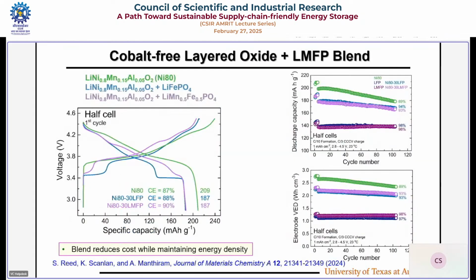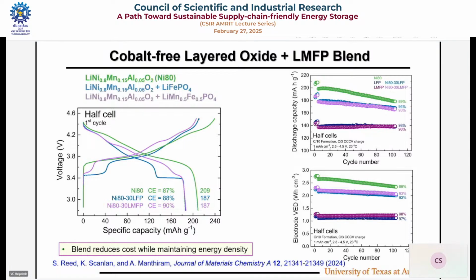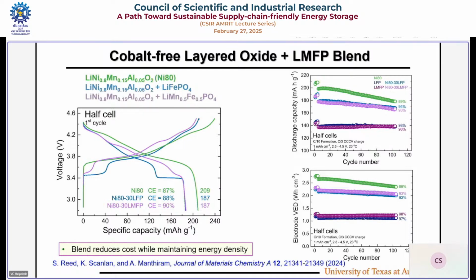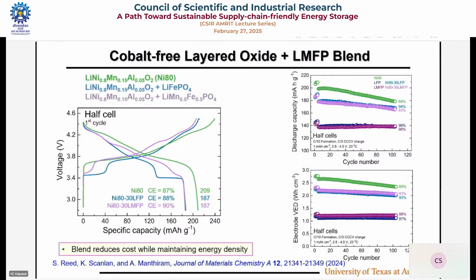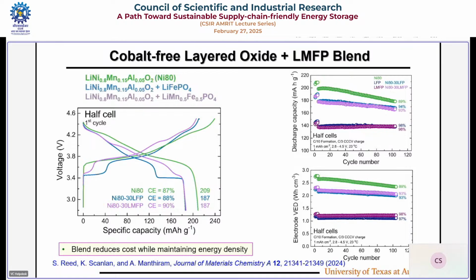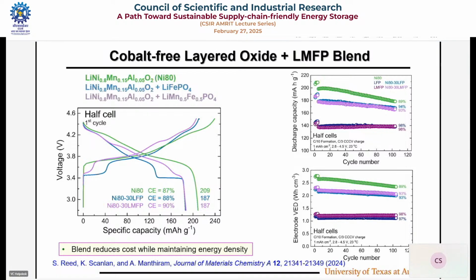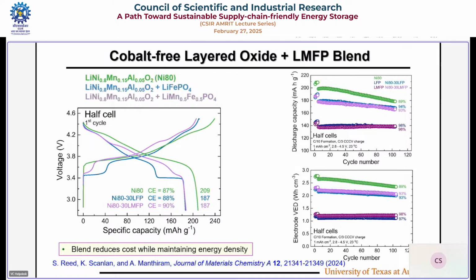Okay, there is another one to reduce the cost further. You can take a cobalt-free layered oxide like I talked about, like this. Then you blend that with this. One beautiful thing I like is this voltage profile. This is layered oxide LMFP blend 70-30. The voltage profile looks more or less similar to the layered oxide. Not exactly, but a very nice plot. This blend can give better cyclability, better safety, and also lower the cost, as you see here. So a lot of advantages.